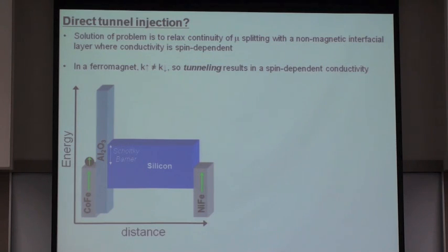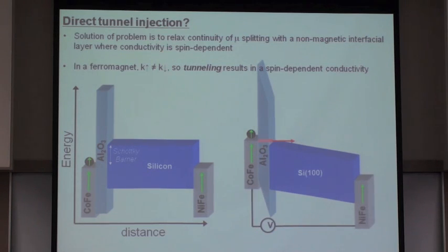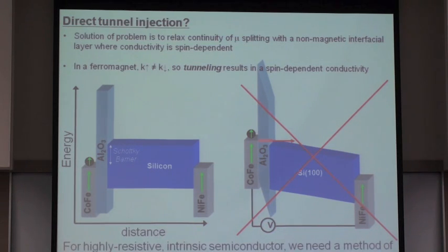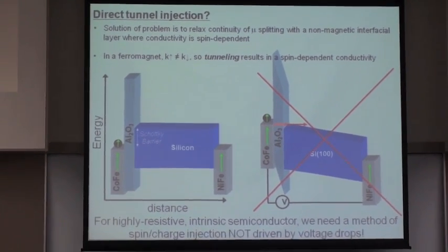But the problem here is that the semiconductor, being so lowly doped, has a very high resistance, and so you apply a voltage from this side to the next, and essentially all your voltage drops across the semiconductor and not across the barrier. And so we can't actually achieve this. This is essentially not going to work when we have very low intrinsic or very non-degenerate doping in the semiconductor. So with that sort of long-winded introduction to the general problem, I'm going to show you how we actually achieve this spin polarized electron injection into this non-magnetic semiconductor completely out of equilibrium.